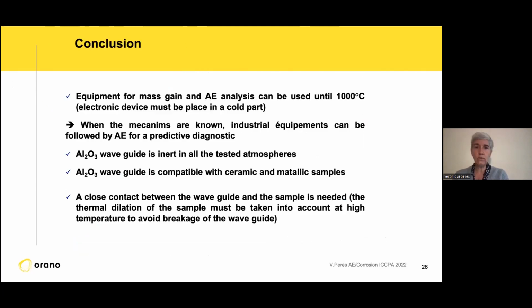So to conclude my presentation, I showed you the equipment we designed to obtain information on mass gain and acoustic emission during high temperature corrosion. We can do it up to 1000 degrees C. The important thing is that all the electronic parts of the system must be placed in the cold part, and we have to be careful about that. And I showed you some different examples.